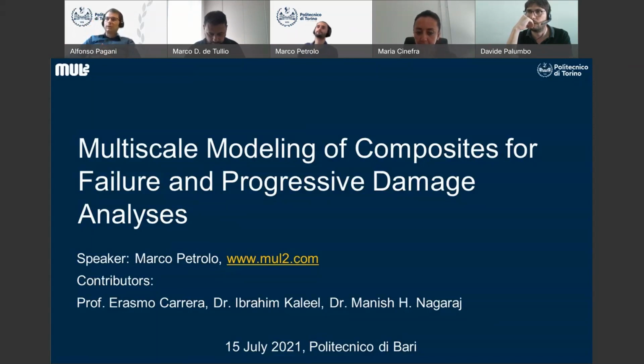The results I have been showing are a combination of the two. For multiscale analysis at the micro level, we are changing the shape of the fiber. So we are varying stochastically the fiber volume fraction by changing the mesh of the fiber in the micro scale. And fiber waviness was accounted for locally by changing the shape of the fiber at each Gauss point. So it's a kind of exact method. If you want to introduce a damage, for example, in a given region, you can also penalize, which is maybe what Marco has done in the voids analysis, right? I don't know if you want to add something.